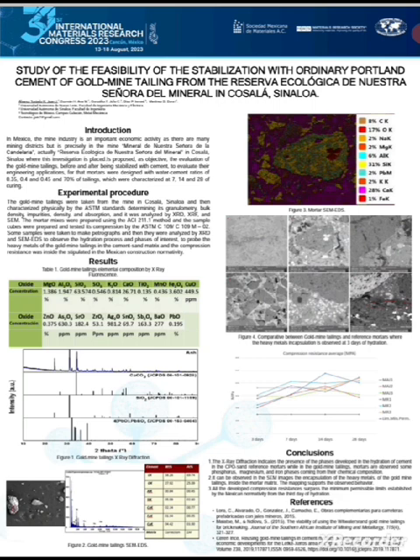In conclusion, the X-ray diffraction indicates the presence of the phases developed in the hydration of cement in the CPO sand reference mortars and in the CPO sand gold mine tailings mortar systems. It can be observed in the SEM images the encapsulation of the heavy metals of the gold mine tailings inside the mortar matrix. The mapping supports the observed behavior. All the developed compression resistance surpassed the minimum permissible limits established by the Mexican normativity for structural masonry since the third day of hydration.